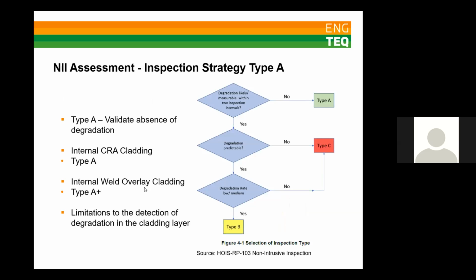So moving on to the first inspection type, which is, as Susan's already introduced, a type A. So this is where no degradation is expected and usually applies to corrosion resistant alloy vessels, most commonly stainless steels, but maybe other materials as well. The most recent update to the recommended practice also allows carbon steel vessels with very low internal degradation rates to be inspected as a type A strategy. So that is, for example, vessels in dry gas service with sufficient inspection history and high confidence that there's no process upsets and things that would cause internal corrosion.